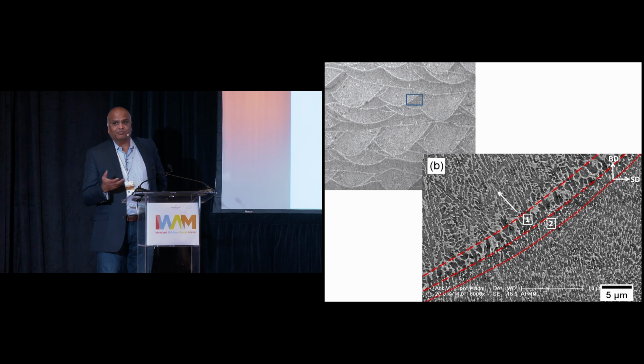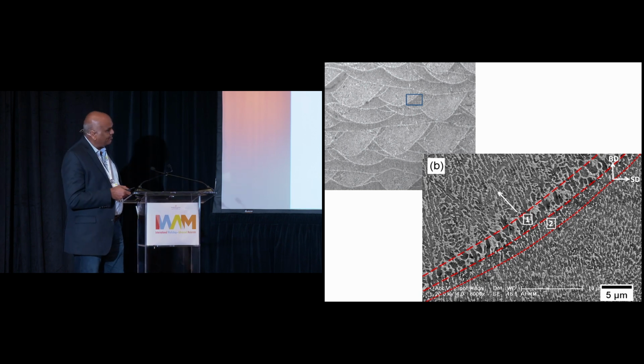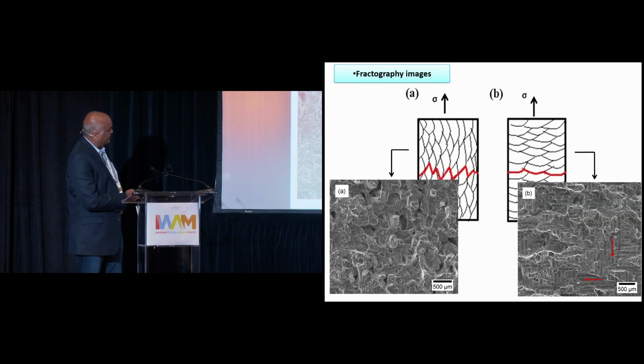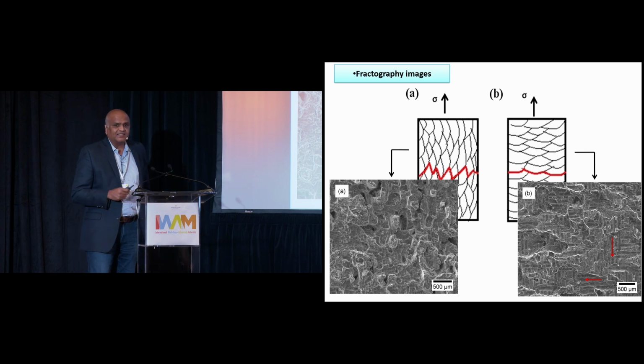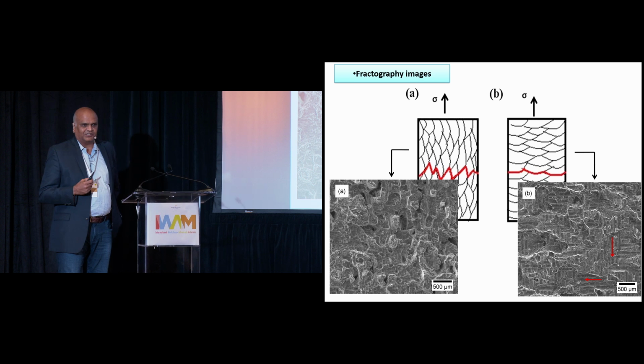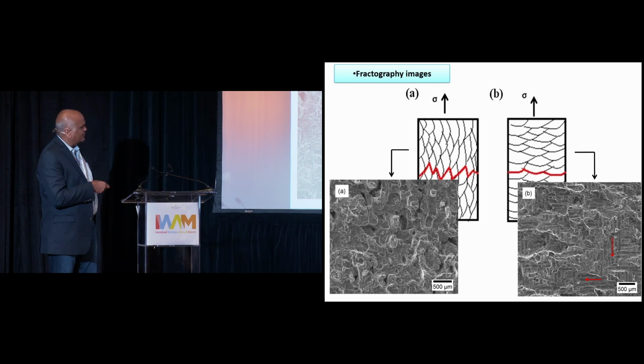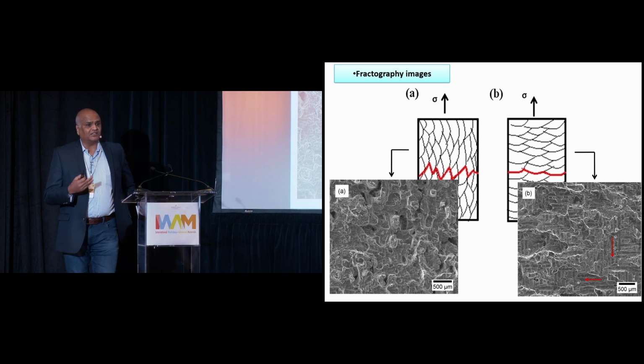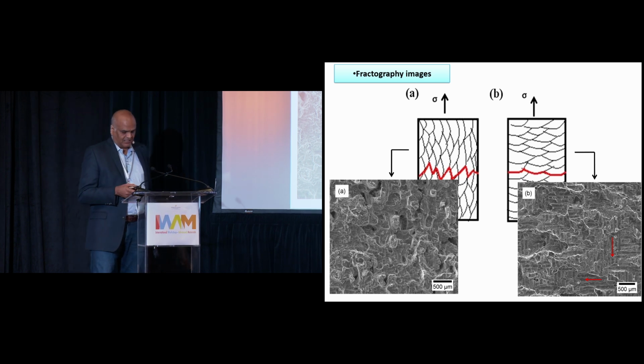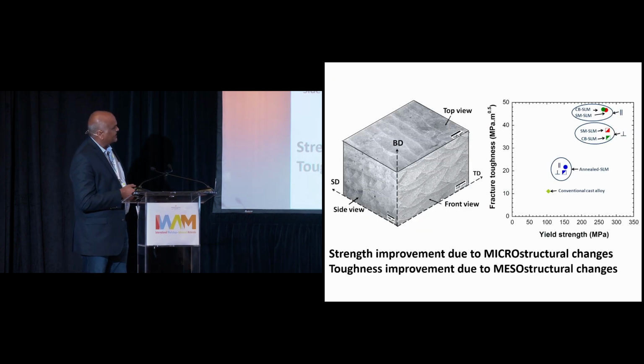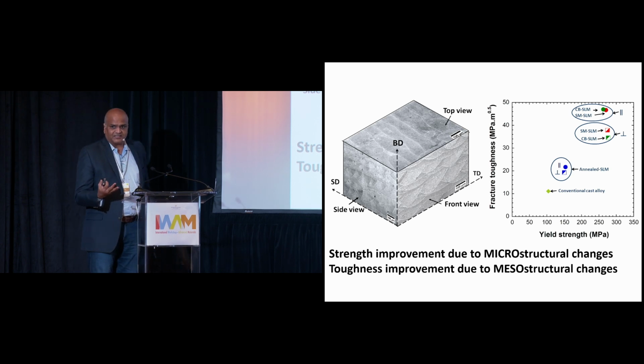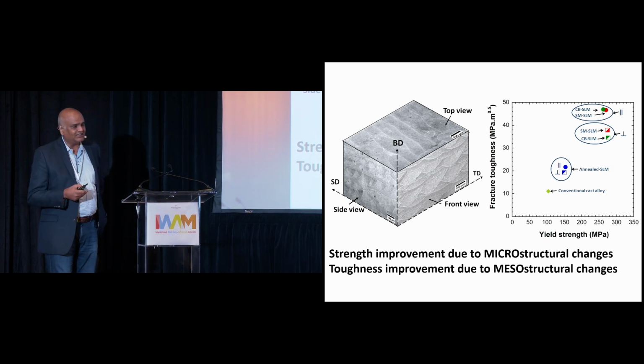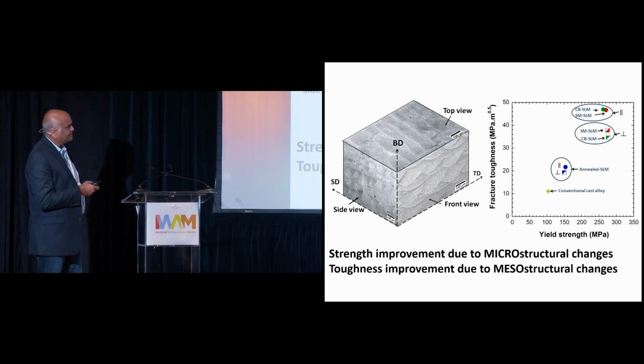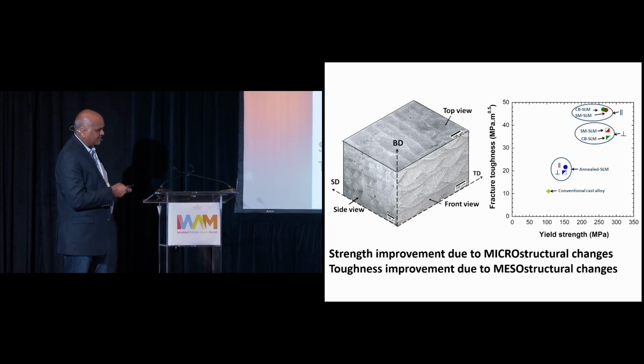And it's actually more three-dimensional in nature. So what happens is, these are the things, they're just schematic illustrations. So the cracks get deflected, and this crack tip tortuosity, a tortuous path in 3 dimensions, as these fractographs illustrate, is what causes the fracture toughness to go up a lot. So the strength goes up because of microstructural reasons, high dislocation densities, etc., whereas the toughness improvement comes about because of the meso-structural features.